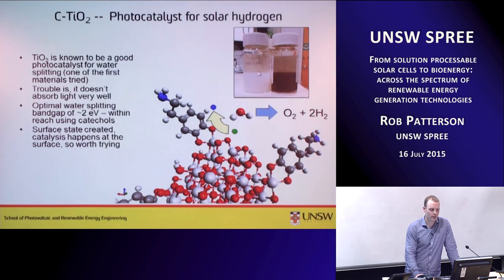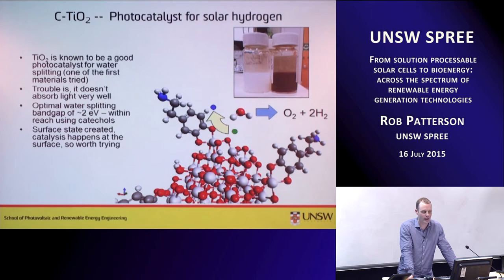So here's a picture of the unfunctionalized material without the ligand on the surface, and here's a picture of the ligand functionalized. And what I don't have here, to make it exceptionally convincing, is a picture of the ligand in solution on its own, because maybe it's red, right? But if you'll take my word for it, it's not. It's clear, water clear, and when you mix these two things, you end up with this strong color for small nanoparticles with large surface coverage of the ligand.